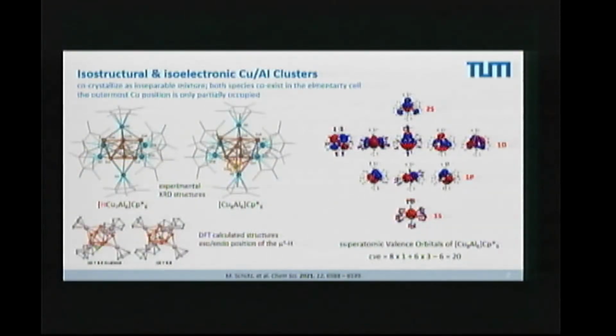So that is basically what the superatom model is about. Now, if you look at these two cases, this was a crystal which contains copper 8, aluminum 6. And if we count that, we come up to 20 electrons. This is filling all this up to the 2s level, and then you have a HOMO-LUMO gap to the next level. Now, if we have the copper 7, aluminum 6, which we can make without the hydrogen, it would be